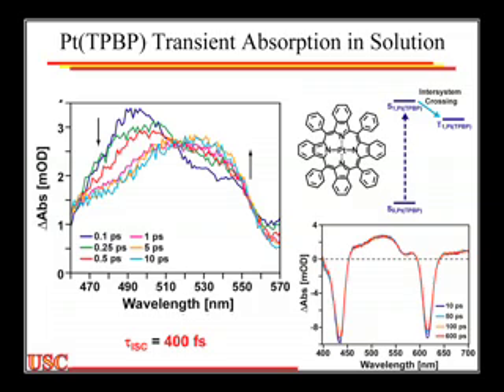So this first peak you saw was the singlet. That's what I made instantaneously. 400 femtoseconds is the time constant for converting into the triplet. So the intersystem crossing rate is about 400 femtoseconds. This is exactly what we expected. This is the same you get for iridium compounds. Any heavy metal will give you a very high intersystem crossing rate.